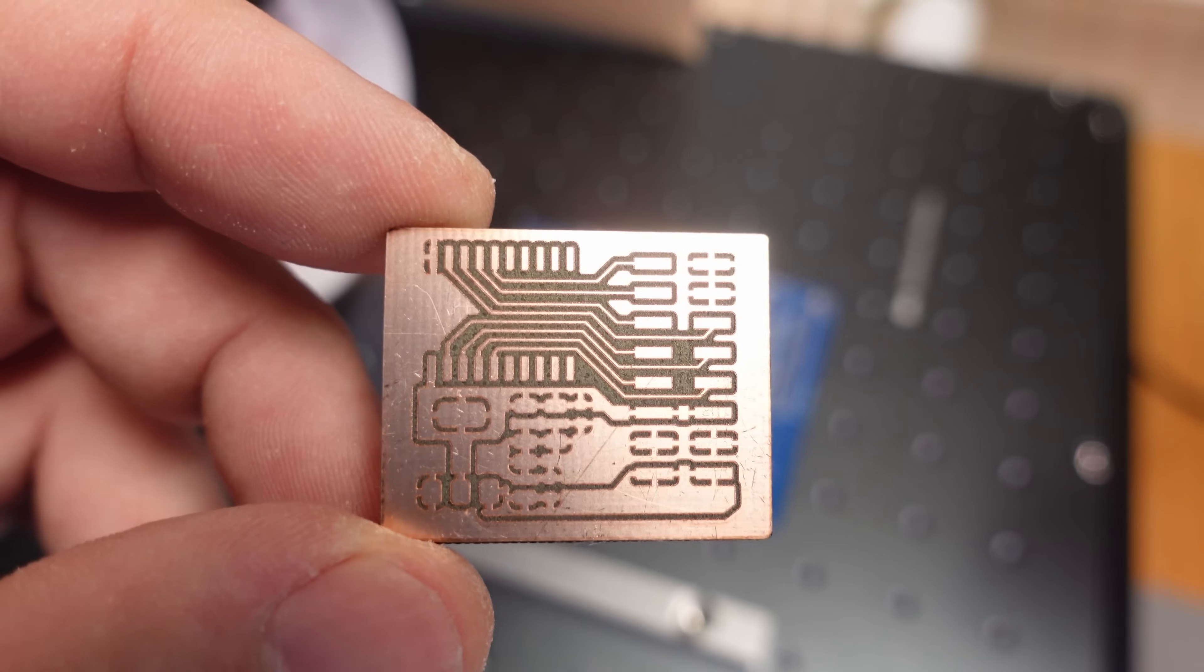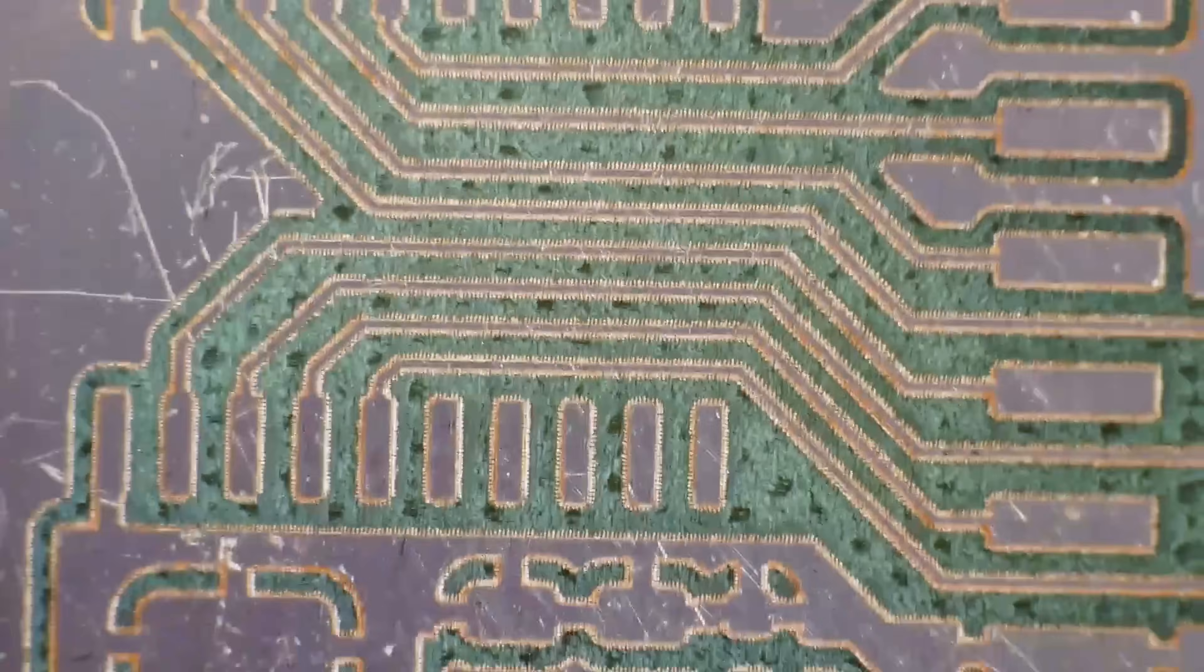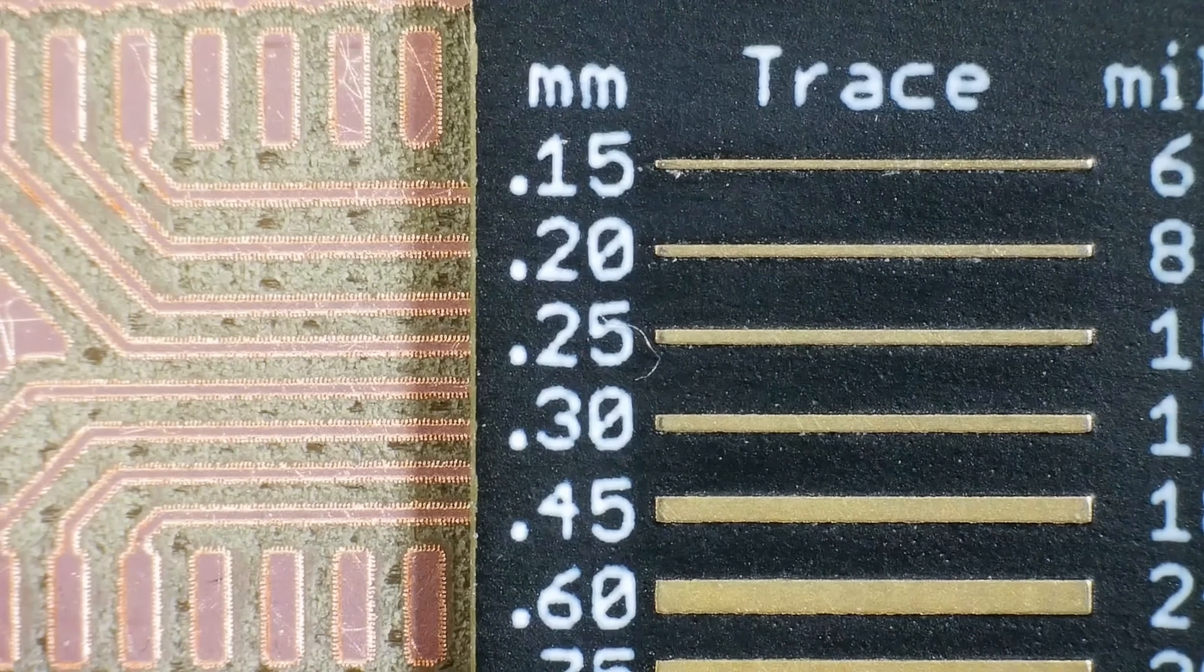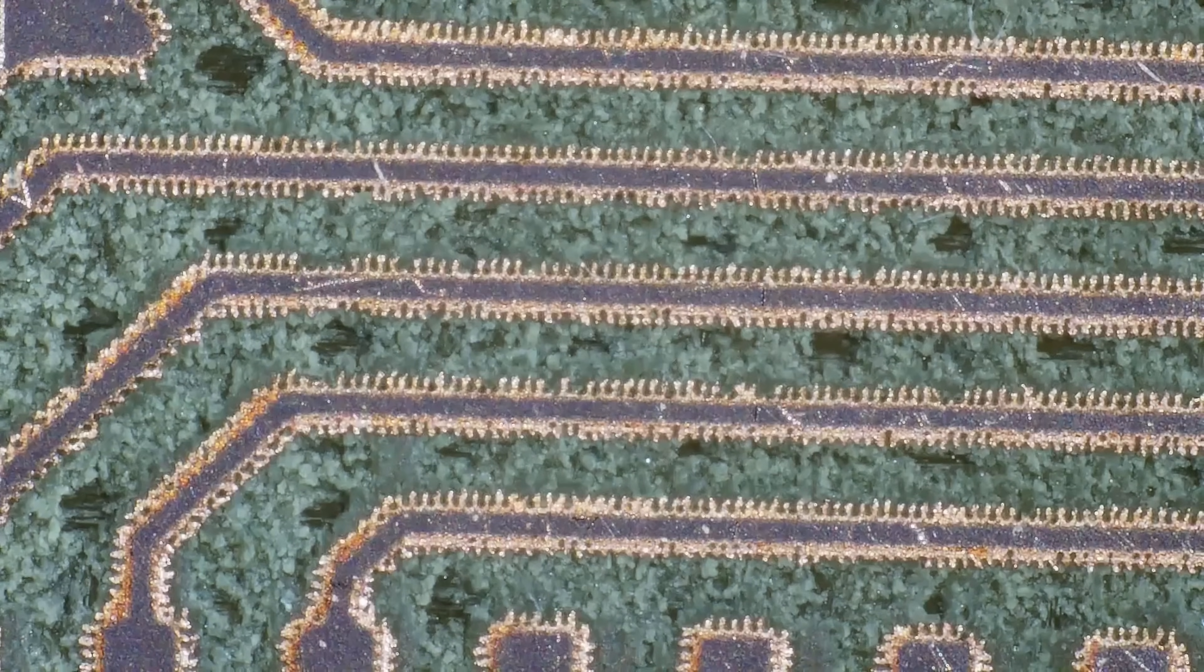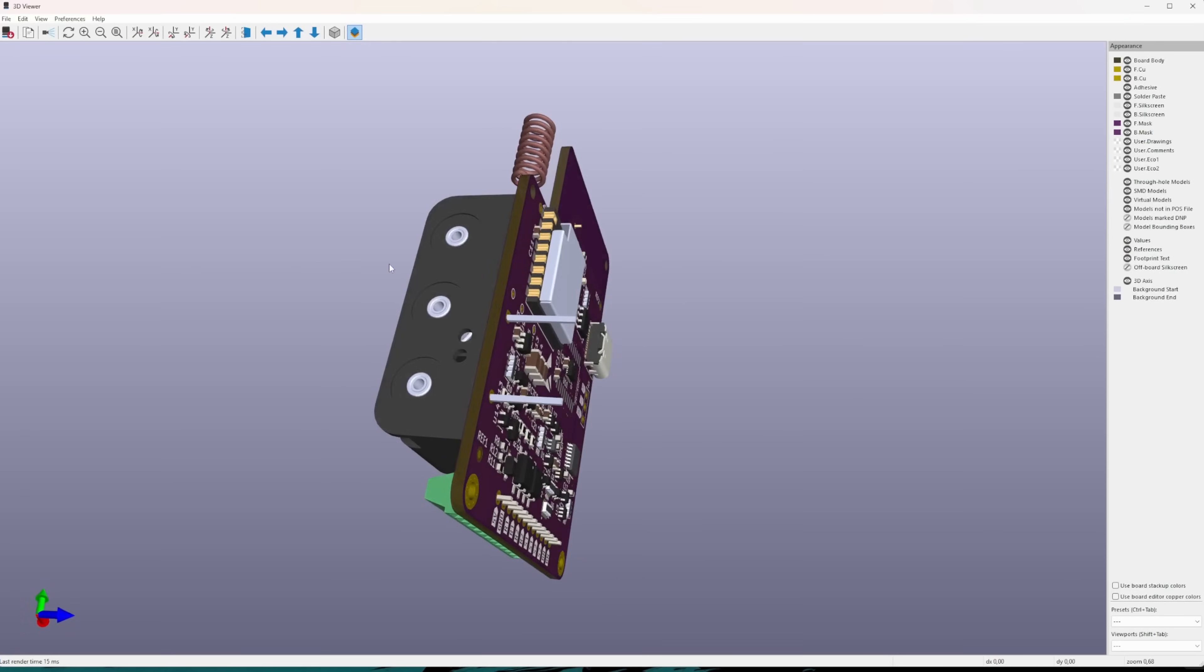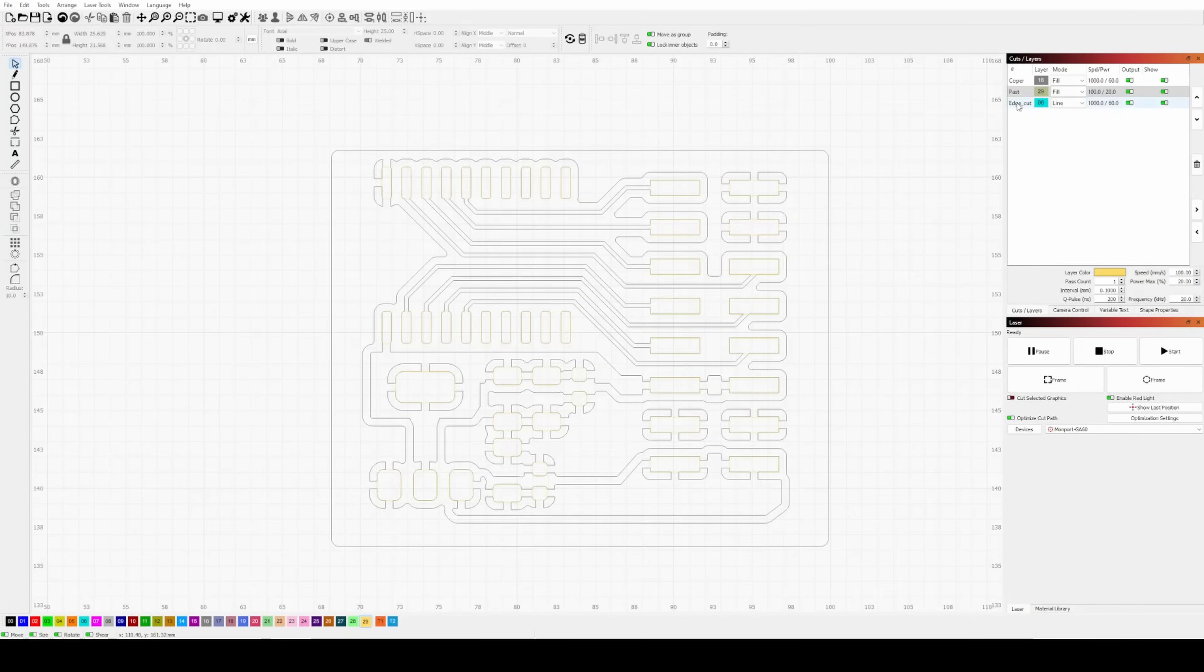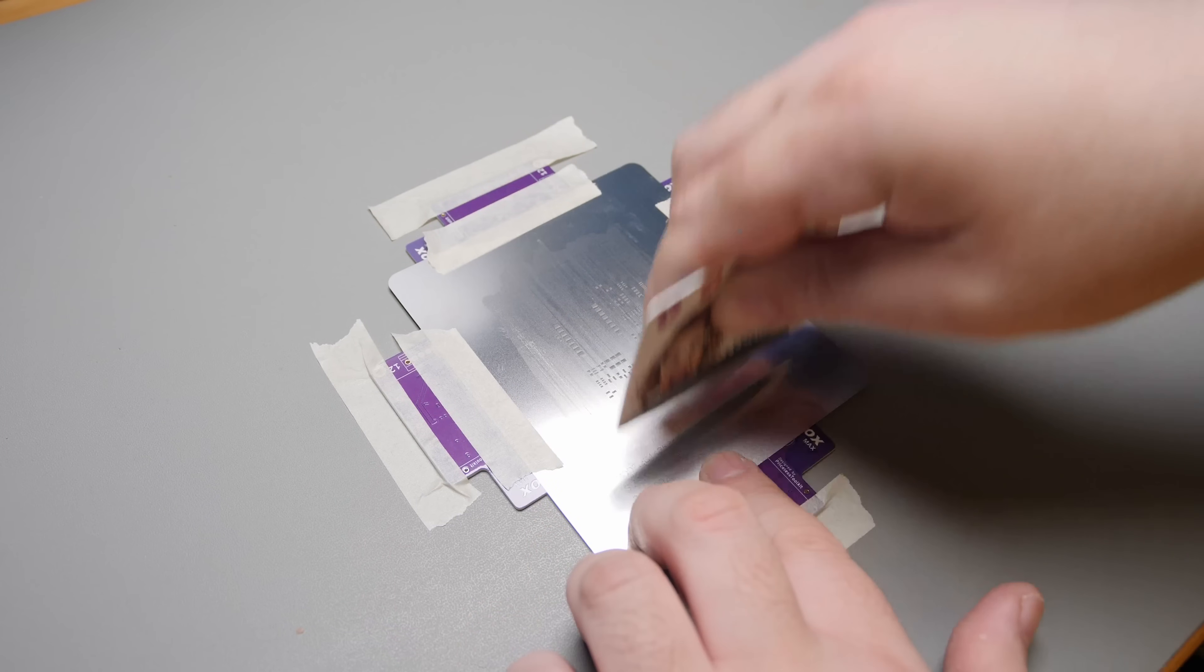Now, let's take a look under the microscope to see how the traces turned out. It looks like all the traces and pads are intact. The trace thicknesses are between 8 and 10 mil, but I do notice some unevenness. Let me zoom in. Ah, now I see. I need to lower the step size to 0.02 millimeters, which should remove all those spikes. With that adjustment, it should even be possible to create traces as thin as 6 mil. If you're interested, I can put together a detailed GitHub guide covering every step, from Gerber files to a finished PCB. If that sounds useful, let me know in the comments.